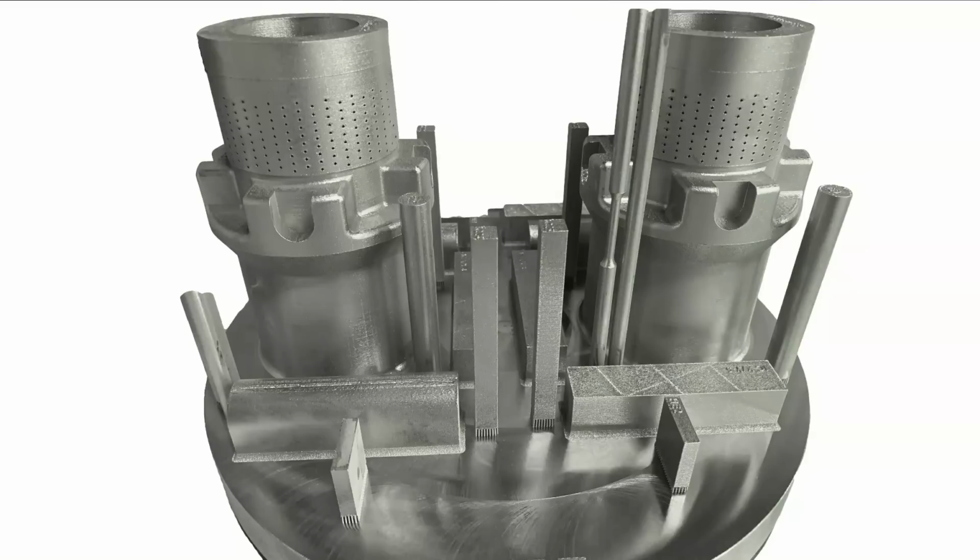And so as an example here, we have some oil and gas choke valves. We've recently had some white papers come out about these, and I would highly recommend you get a hold of those and read them. But for the quality of part that they're printing here and for the importance and criticality of this part, they needed to ensure that the material properties are what they expect them to be. So they include these witness coupons that can be tested after heat treat, right? So you have the printing portion, you have the chemistry portion, you have the heat treating. All of that can have a drastic effect on your end state. And so by including those witness coupons, you can then test the material properties in that end state to verify they are what you're looking for.